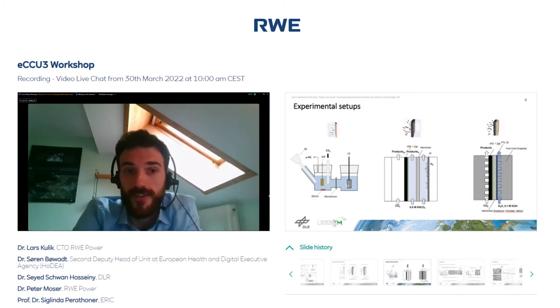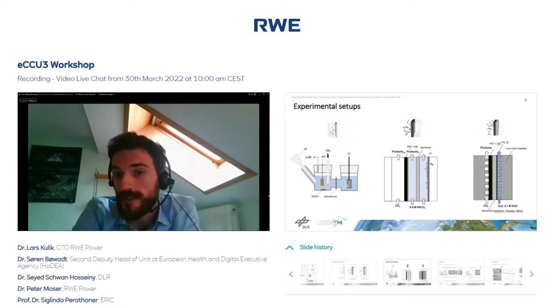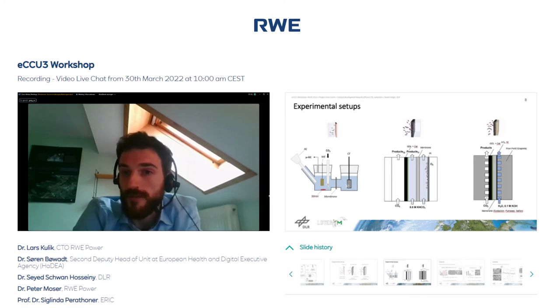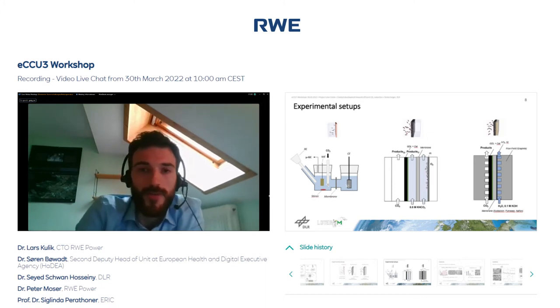And slide 8 shows the schematics of how these cells look in our lab. On the left side, there's the so-called H cell, where just the metal is dipped in a solution where CO2 is bubbled in. In the middle, the flow-through cell, where we have two electrolyte pumps that pump the catholyte and the anolyte, vice versa, that are separated by a membrane. And then CO2 comes from the backside of the electrode. On the right side, this is very similar to a fuel cell setup, where just the membrane is basically separating the two compartments. Just in this case, we also have water present, basically like an electrolyzer setup, not a fuel cell.